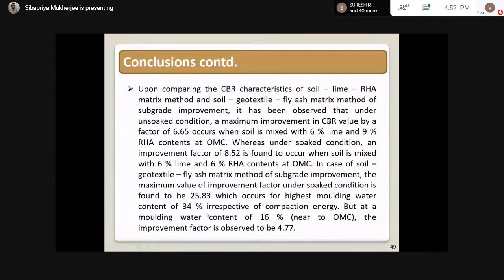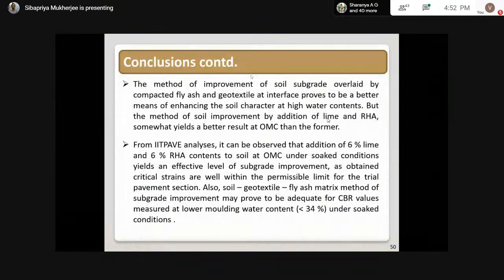But at a molding water content of 16% near OMC, the improvement factor is 4.77, it is falling. So the method of improvement of soil subgrade overlaid by compacted fly ash and geotextile at interface proves to be a better means of enhancing the soil character at higher water contents. But the method of soil improvement by addition of lime RHA somewhat yields a better result near OMC.